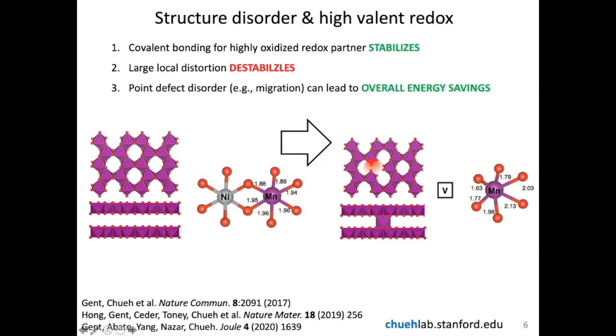So this is one of the key stabilization mechanisms behind why you're able to oxidize the material to a very high valence and have the transition metal move around and yet not leave the material. And this is the ability to accommodate short bonding between metal and oxygen and oxygen and oxygen. Another way to view this is to simply look at the coordination number between the metal and the oxygen. In the left structure, each of the transition metals is coordinated to six oxygen, but on the right, the transition metal is coordinated to only five oxygen. So this decreased coordination of the metal and the oxygen is one of the key stabilization mechanisms, allowing more flexibility in the structure, thereby reducing the tendency for oxygen to depart from the material and stabilizing it. This is one of the key design rules behind how to achieve high voltage cathodes.